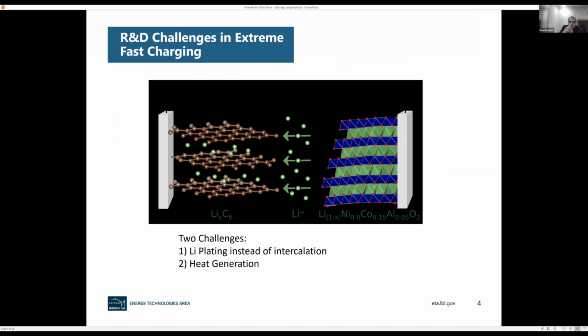That's called intercalation. But the problem is that when you do extreme fast charging, the chemical reaction is happening so fast that the lithium, rather than intercalating, cannot diffuse fast enough, right? So you start to plate right here. It doesn't insert, you just start to plate, right? So that's a major challenge. And second is enormous amount of heat generation, right? As I mentioned earlier.